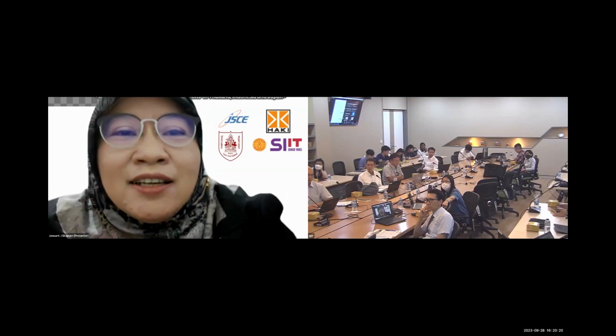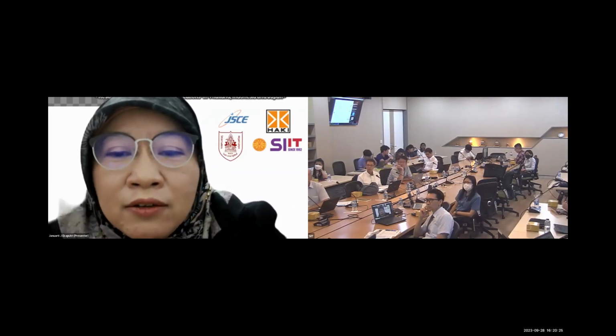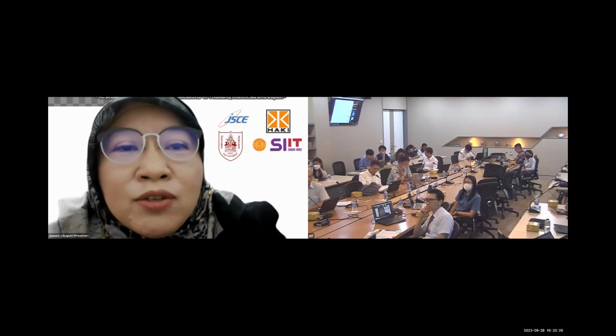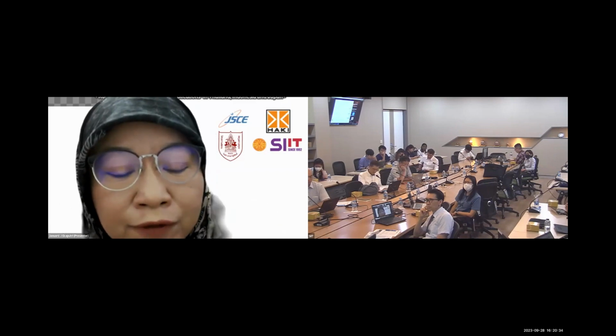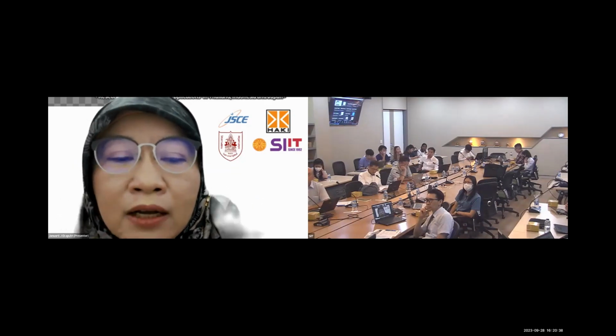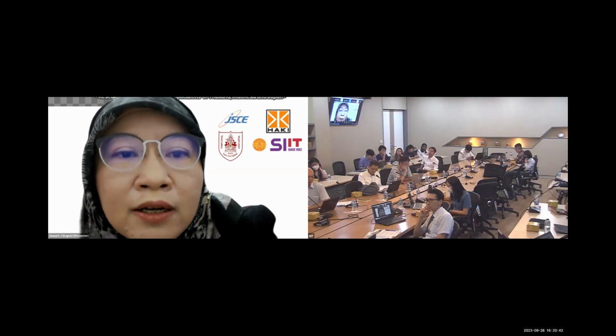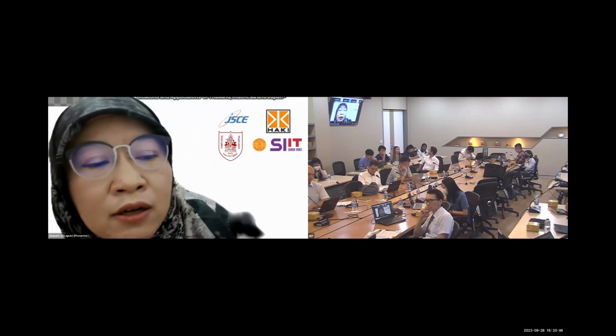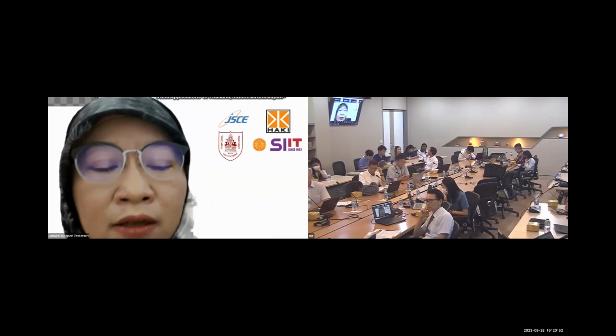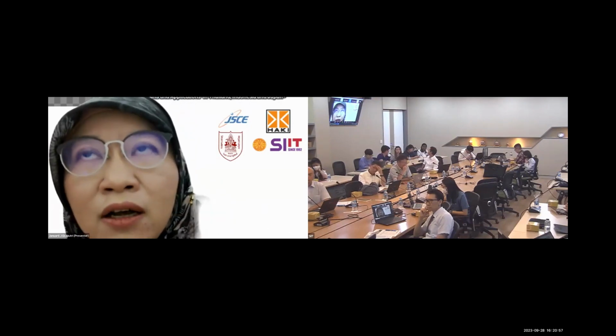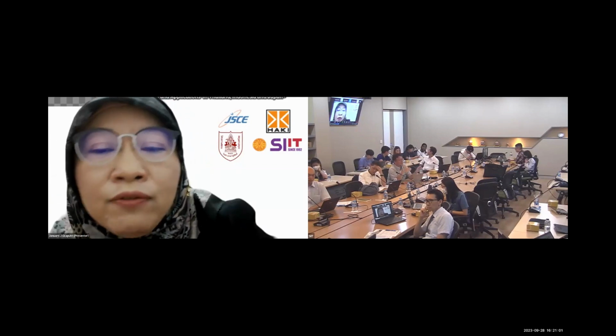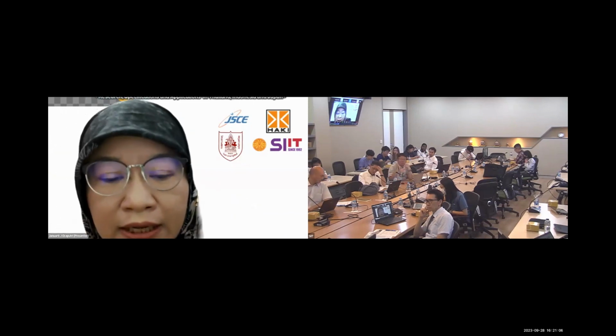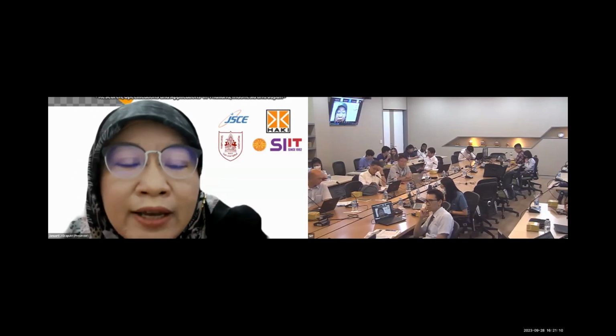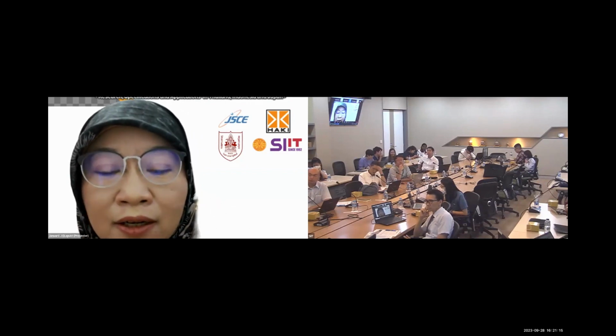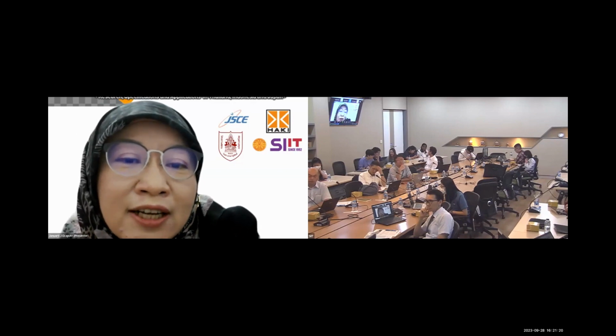For the first question related to the shrinkage, some people say that the shrinkage of geopolymer is very large, and some people say that geopolymer shows very low shrinkage, and we have found that it depends on the quality of fly ash. Here in Indonesia, we have fly ash from different boilers, for example, pulverized coal combustion boilers that burn the coal at up to or more than 1,000 degrees Celsius. So it produces a high quality fly ash, and the dissolution of fly ash in the alkali system is really good. This kind of fly ash will show lower shrinkage. However, it depends on the mix proportions.